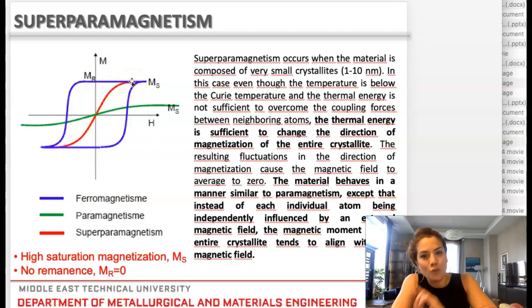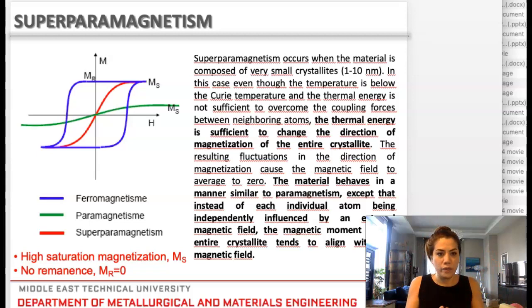The reason why they put a super in front of paramagnetic behavior is because it is fairly strong, okay? So with the same amount of magnetization compared to a regular paramagnet, we're getting much higher saturation flux densities. But what happens is, after a certain size, as you go smaller, each crystal domain acts like an atom, okay? So a ferromagnet becomes a superparamagnet below a certain size. The reason for that is these domains are acting like individual atoms with paramagnetic behavior.